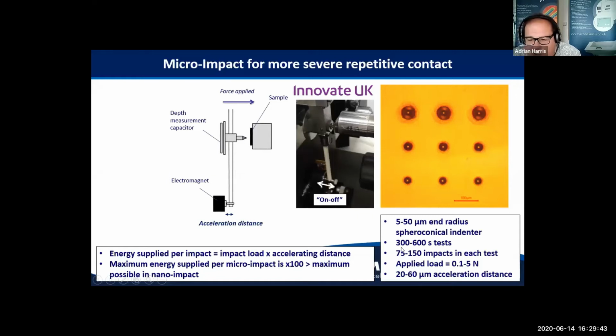We're back to using a shorter duration test. Typically, we go for 300-second tests. As you saw in the previous slide, we'd gone to 600 seconds. We had no failure. So we try to keep tests in a 5-minute period. Typically, a 5-minute test would be 75 impacts. This is really the conditions that we prefer in order to do multiple repeat tests on multiple samples in a time-efficient manner. Impact loads go right up. As you saw, we used 150 millinewtons on the previous slide. Just here, 150 millinewtons. Now we can go right up to 5 newtons, and we're increasing the acceleration distance.